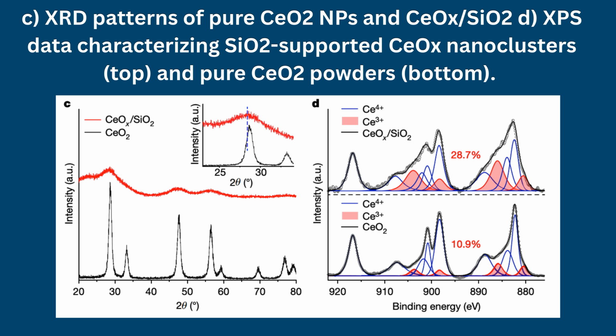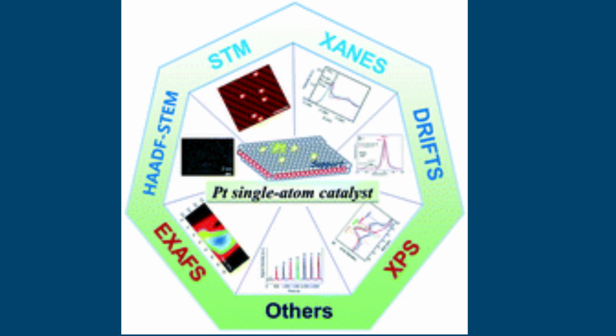X-ray absorption spectroscopy, XANES/EXAFS, confirms atomically dispersed platinum species with no platinum-platinum coordination. Infrared spectroscopy, DRIFTS, demonstrates characteristic CO adsorption on isolated cationic Pt sites. Collectively, these data establish that platinum atoms are site-isolated and strongly coordinated to CeOx nanoclusters.